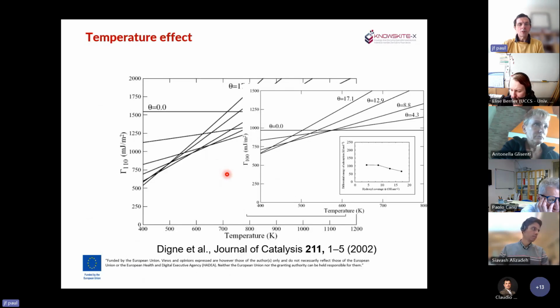And if you want to take into account the effect of the temperature, you will have to introduce this effect on the chemical potential of the molecule in the gas phase. This can be done using statistical thermodynamics. We consider in general that the effect of the temperature on the solid is quite small, and that the most important effect is due to the evolution of the entropy in the gas phase.